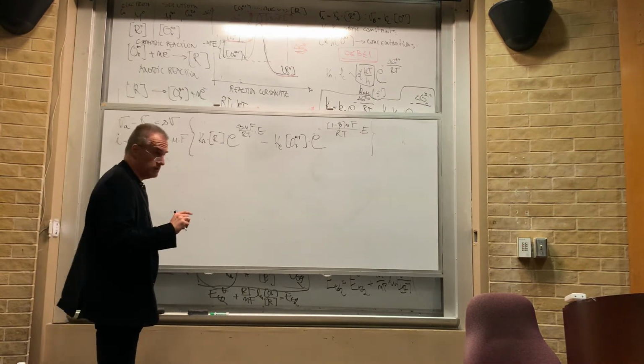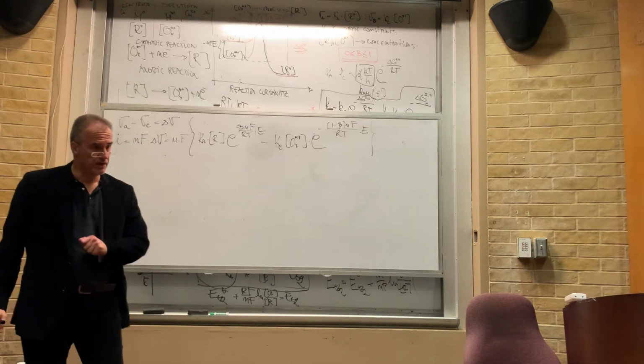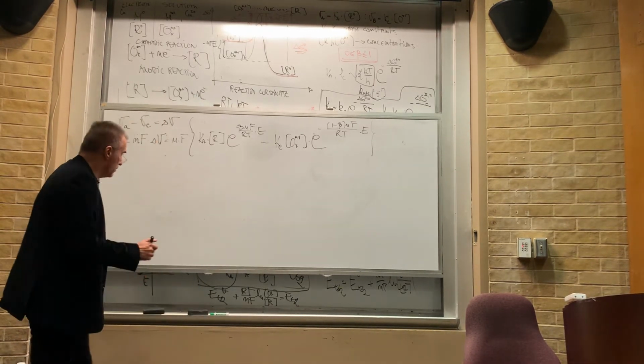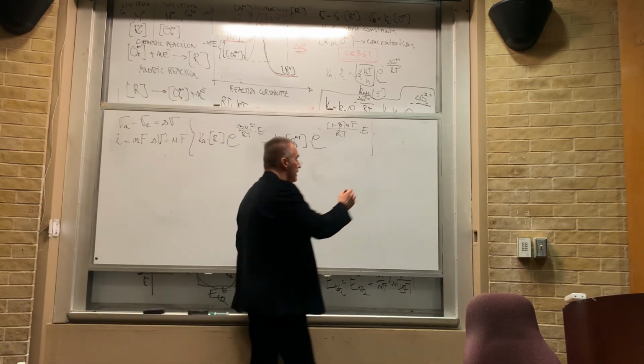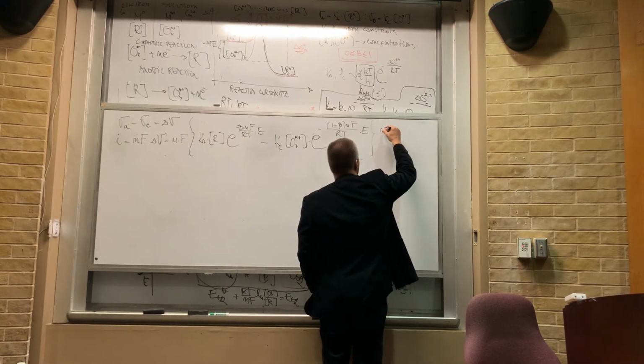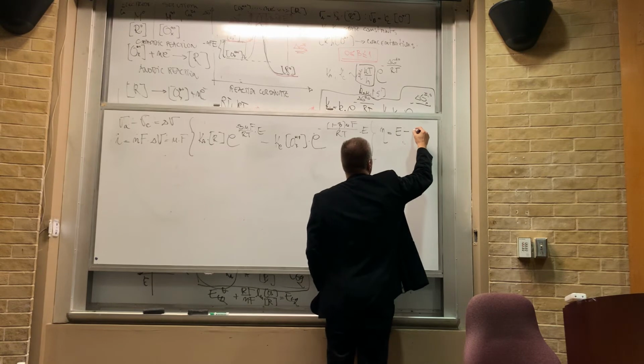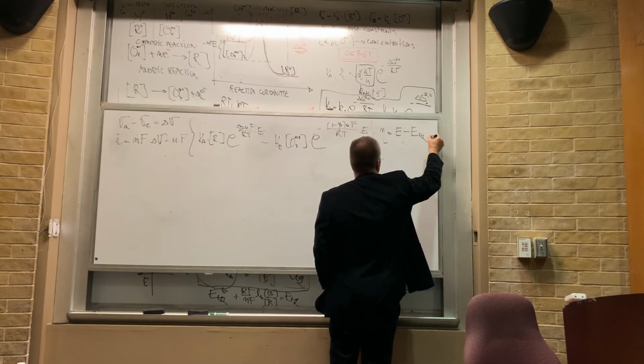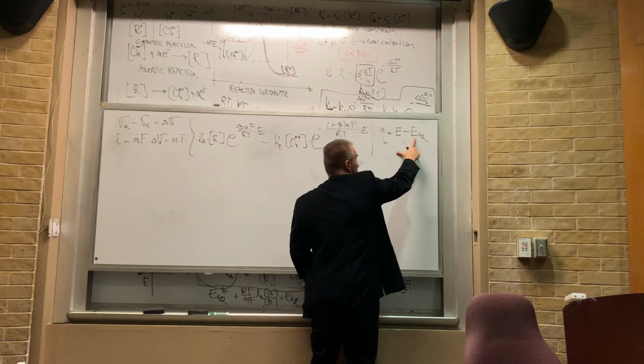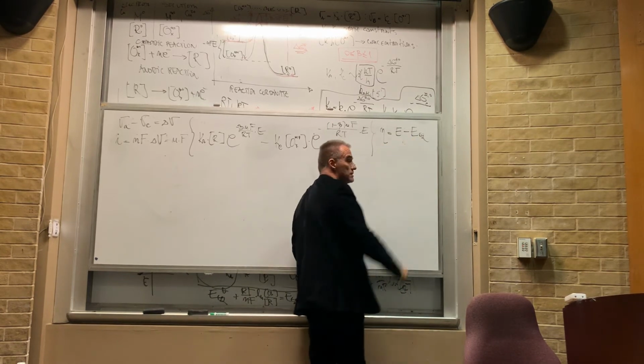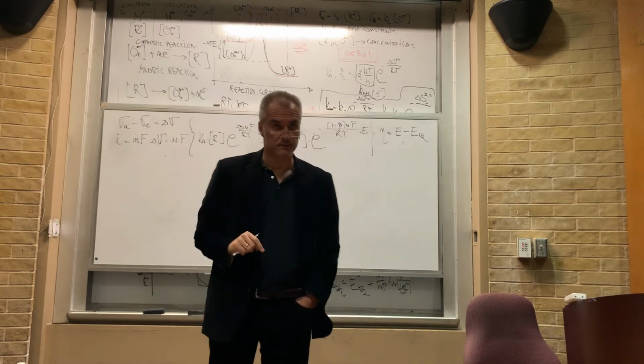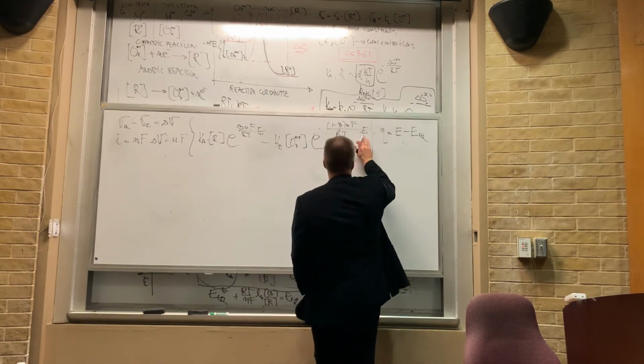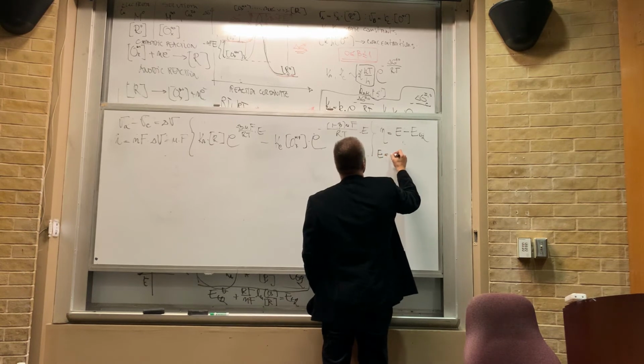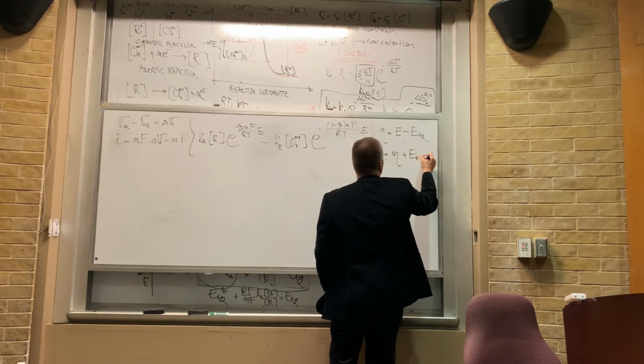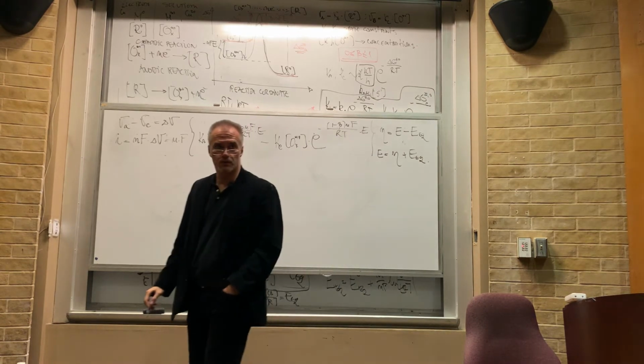Now let's say this E is some arbitrary potential, but we want to have a different rate. So we either drive the reaction in the anodic or cathodic direction. And what I'm going to do is a little trick, introducing a notation in which this is an overpotential, equal to E minus E equilibrium. So whatever potential I apply across the interface minus the potential at which the interface is in equilibrium gives us this term, which we call overpotential, eta. What that really means is that this E, an arbitrary applied potential, is equal to eta plus E equilibrium. Right? Everybody clear with that?